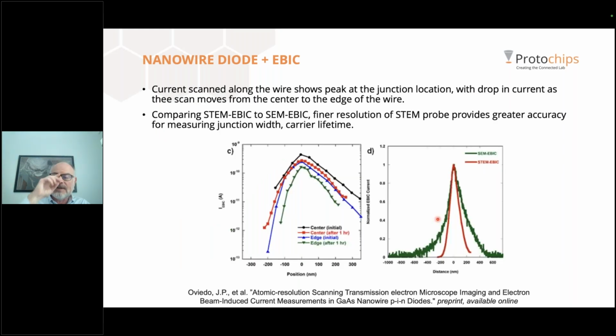So here what the authors did is perform a line scan, so a 1D scan along the length of the nanowire diode. And there's lots of interesting data here. First, you see the shape of this curve on the left, this peak. The peak reveals the location of the diode junction. So when a beam sweeps across a semiconductor junction, the current goes up because the electric field that's present in the junction can sweep away those charge carriers and collect them as current.